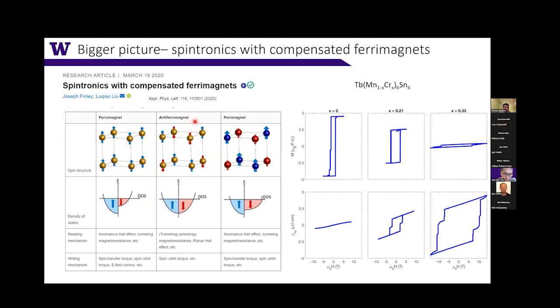Therefore, people begin to think about antiferromagnet spintronics, where the moments can switch on a much faster time scale. And also there's zero stray field, so there's no interference for the neighboring memory cells. Now the problem is that here you don't have any magnetization, so it's very difficult to control. And you also have no Zeeman splitting in the Fermi level, and no anomalous Hall effect, so it's also very difficult to read out.